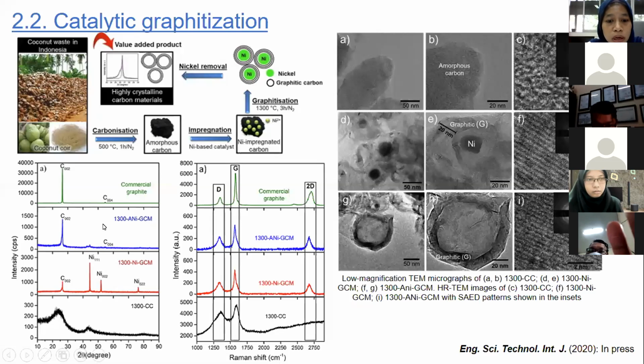Okay, the XRD of the sample treated with nickel, this one is before acid treatment and this is after acid treatment, contains a strong peak centered at approximately 26.5 degrees. This diffraction peak corresponds to the 002 plane of graphite, and it was also observed in the XRD pattern of commercial graphite. We also compare with the commercial graphite.